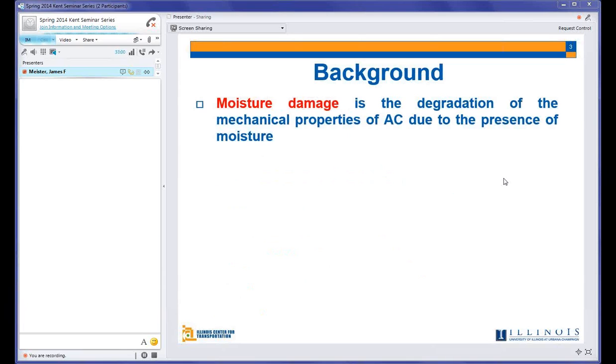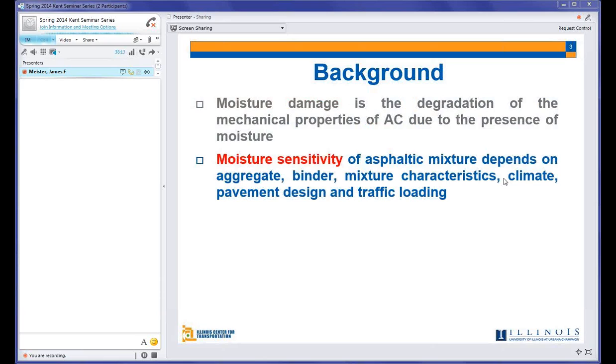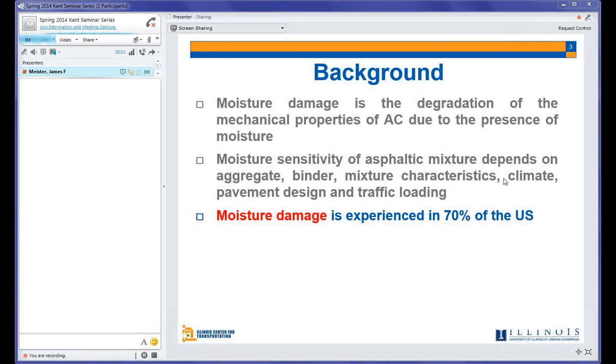Moisture damage, briefly, is defined as a degradation of asphalt concrete mechanical properties due to the existence of moisture. And the susceptibility or sensitivity of asphalt mixture to moisture basically depends on several factors. Most importantly, the aggregate and binder that we are using in the asphalt mix, the mixture characteristics between those two components, the climatic conditions, of course, this is so important, the pavement design, and the traffic loading. It is good to know that 70% of our roads here are suffering from this phenomena, the moisture damage.